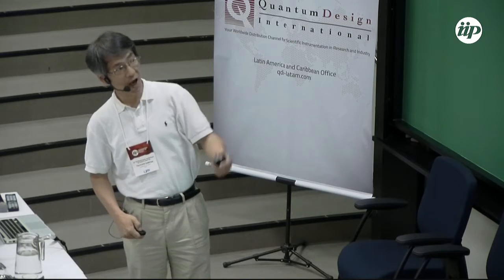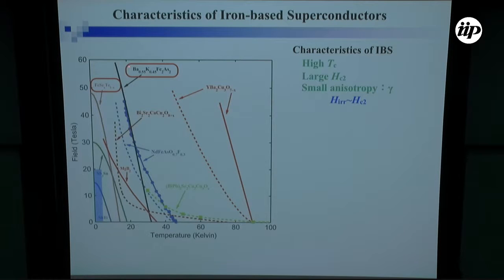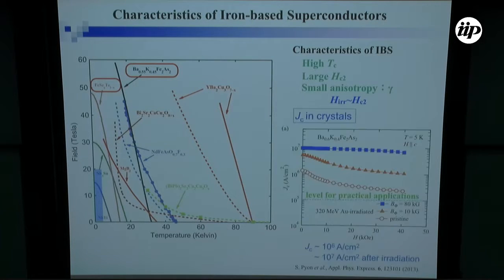This graph, also introduced by Professor Marr, shows the characteristics of the iron-based superconductors. This is barium-potassium-122 or 111 system. They both have a high-TC, a moderate high-TC, 36 or 15 Kelvin, and large HC2, up to 50 Tesla. What's very interesting and important here is they also have a very small anisotropy, which makes the irreversibility line very close to this HC2 line.